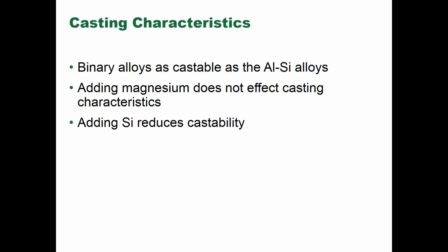Interestingly, adding magnesium does not really affect the casting characteristics. We've tried some very high magnesium levels in these alloys, and it has been successful. Ironically, for those of us in the foundry business that cast a lot of aluminum silicon alloy, the element that has the biggest negative effect on aluminum cerium alloys from the standpoint of castability is silicon. You're more effective in copper alloys than in silicon alloys, which is interesting, and we're not sure of all the reasons why that's the case, but we've been able to demonstrate it a number of times.